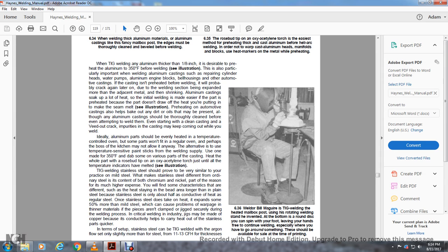TIG welding stainless steel should prove to be very similar to the practice with mild steel. What makes stainless steel different from ordinary steel is its content of both chromium and nickel, and its higher expansion. You will find some characteristics that are different, such as the heat staying in the bead area longer than with steel, because stainless steel is only about half as good a conductor of heat as regular steel. Once stainless steel takes the heat, it expands some 50% more than mild steel, which can cause warpage problems in thinner materials, so parts should be clamped and jigged securely during the welding process. For critical welding, industrial jigs may be made with copper as the conductor to help carry the heat out of the stainless steel part quicker.